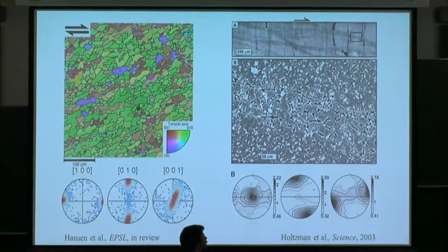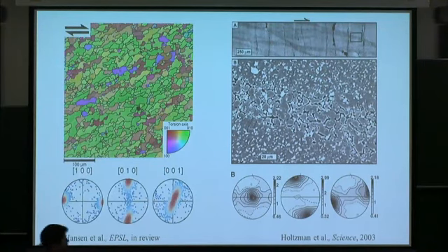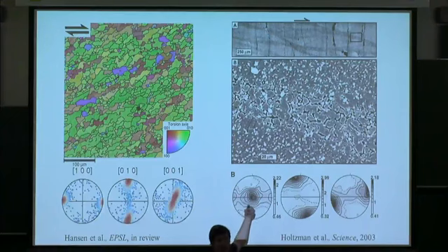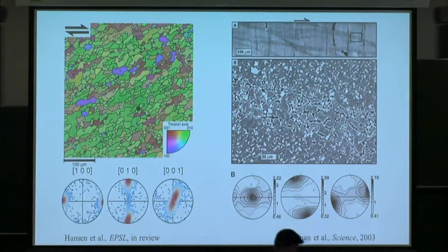You can contour this, and it's like a probability distribution function, or as Neil is calling it, an orientation distribution function. And on the right is the case, this is from Ben Holtzman's work, where now there's a melt present, and it's segregating into these melt-ridge bands, on a length scale larger than the grain size. The key observation here is, on this side, 1, 0, 0 axes are in the plane of the screen, and in the case with the melt segregation, they're at about 90 degrees to that, the maximum in this distribution. Okay, so it's subtle, and you may think it doesn't matter too much, but it is a key indicator that there's something very, very different happening at the grain scale.